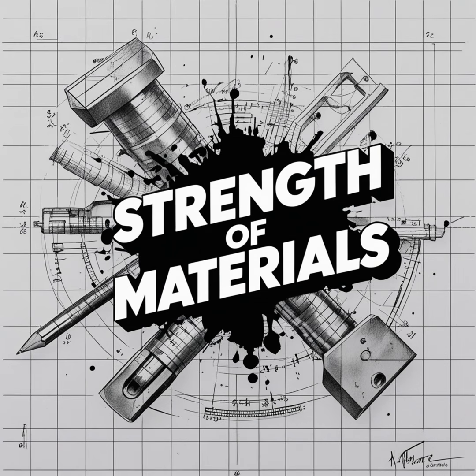It does, but the grains are so unimaginably tiny relative to the plastic zone at the tip of the crack that the material effectively acts as a homogeneous, continuous solid. The crack simply slices straight through the macrostructure. It doesn't see the individual grains as structural obstacles because they're just too small to deflect the massive energy of the crack tip. But what happens when we move to the microcrystalline regime, where the grains are 50 or 100 times larger? Now, the crack encounters massive, distinct crystal boundaries.